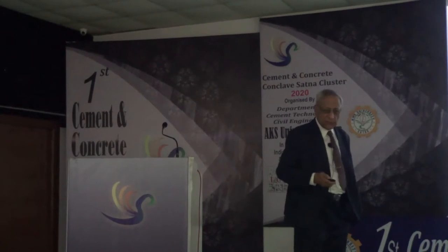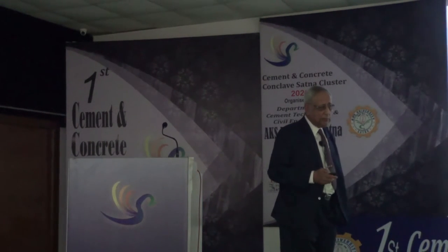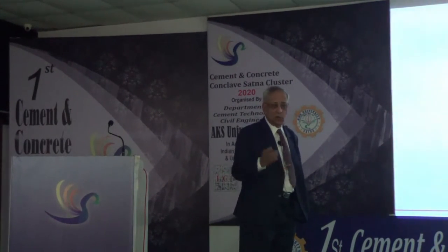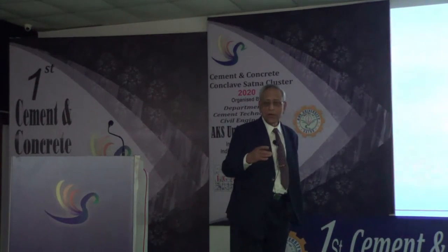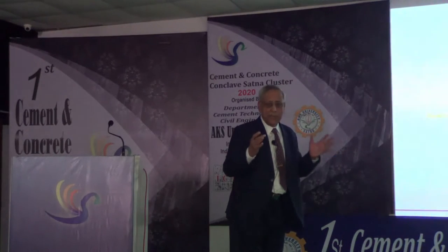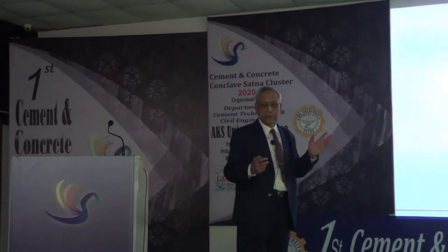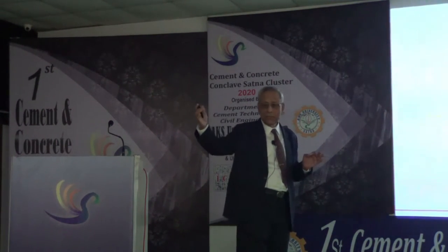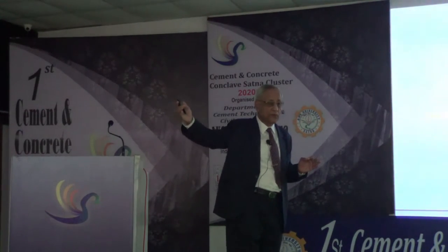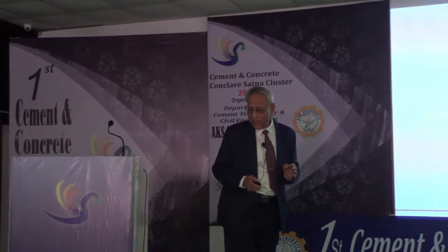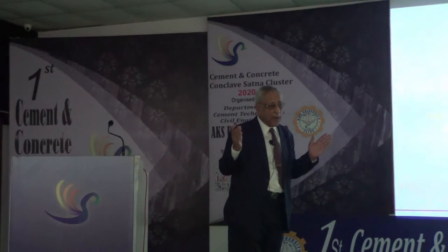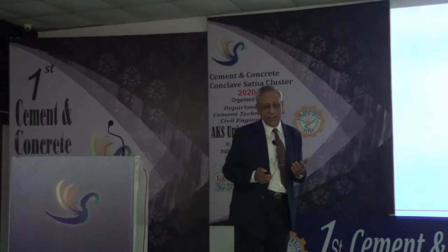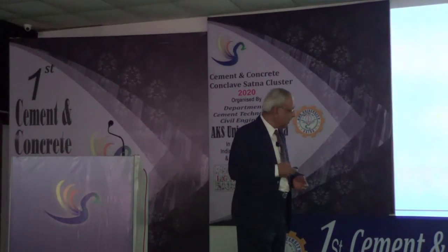Then there is segregation of the concrete, meaning you have not really been able to compact your concrete as it should be. Therefore, while you place the concrete, the material segregates because it has an assemblage of materials where particles range from micron size to 20 millimeter in general, if you have not gone for even 40 millimeter aggregate size. So you are basically using a wide spectrum of particle sizes in concrete, and if you have not taken care, then obviously there will be segregation of concrete.